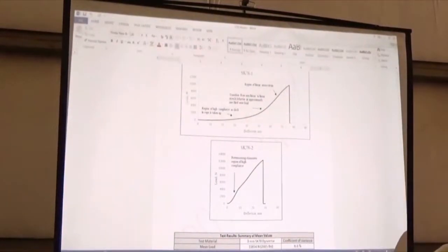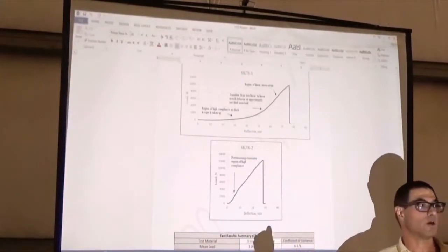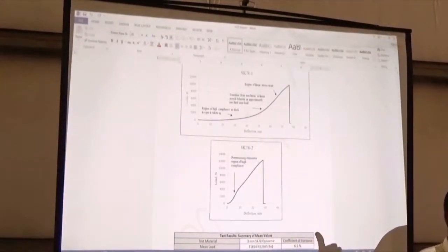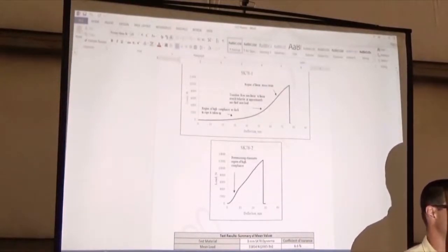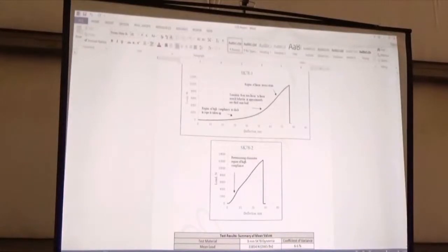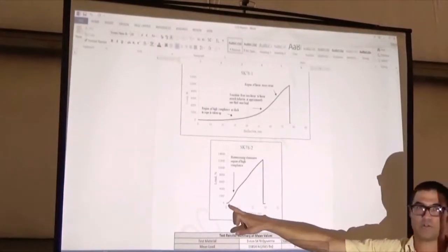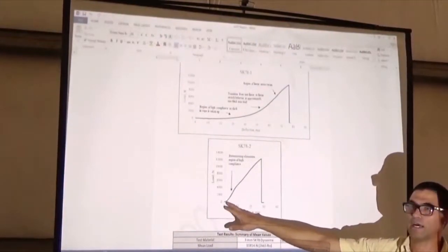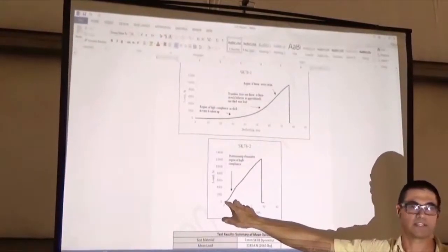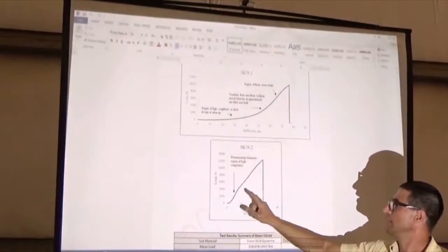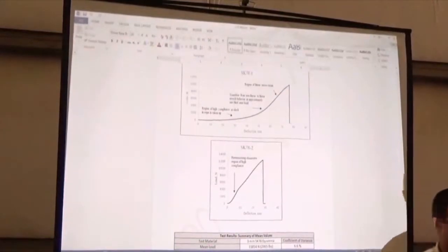So what I realized is that if you're going to use something like Dyneema for a control cable, you have to do a pre-stretch. And you do a pre-stretch to say 50% or 70% of your ultimate load that you plan to put on the cable. And then when you do that, you end up with much lower compliance. You basically remove all of that compliance, and you end up straight on your linear part of the curve.